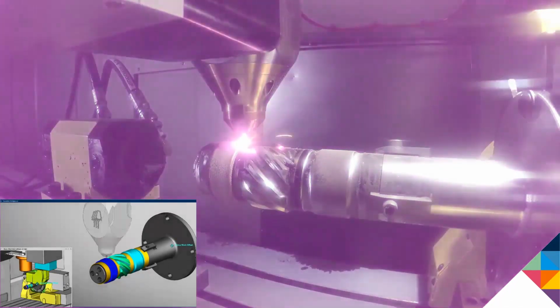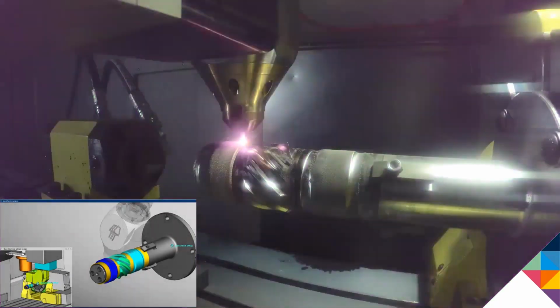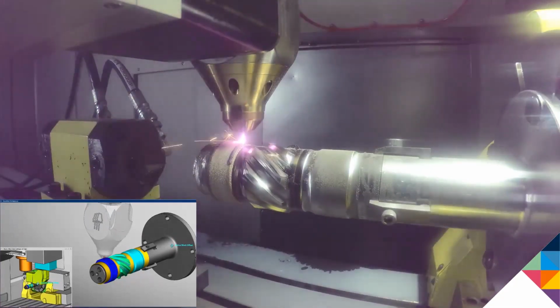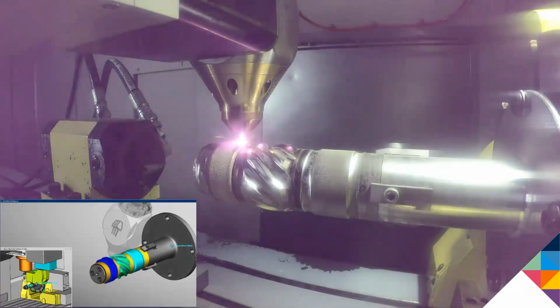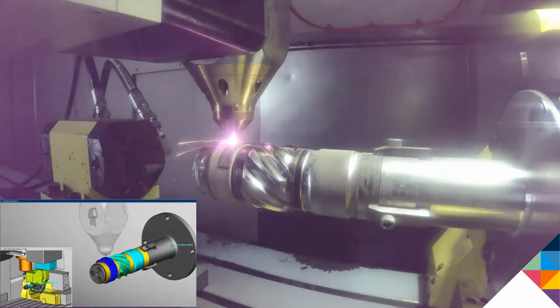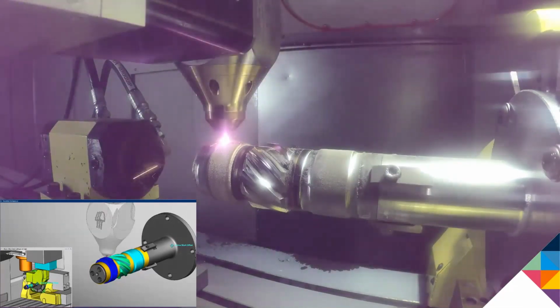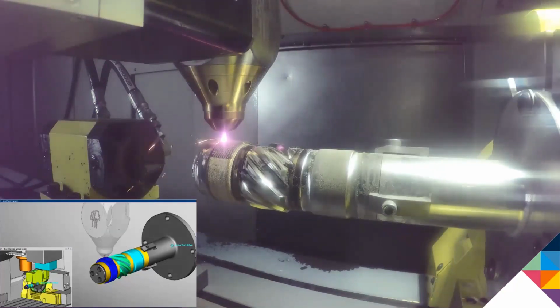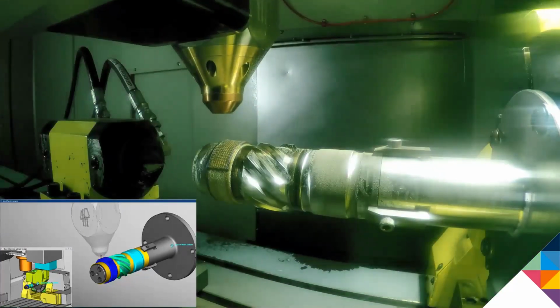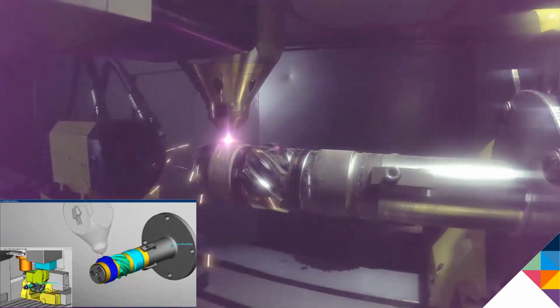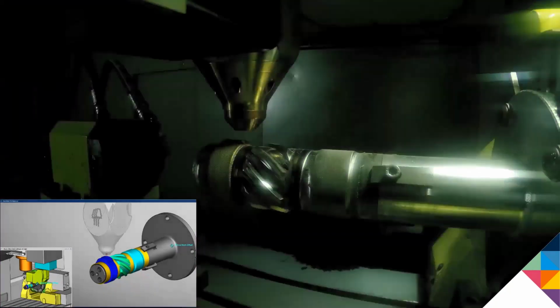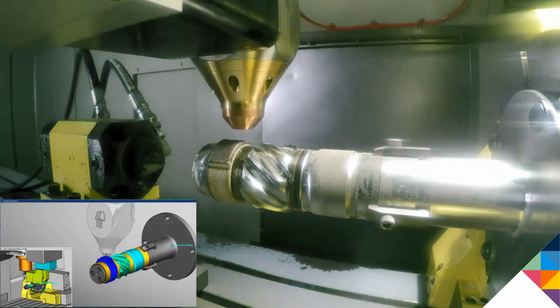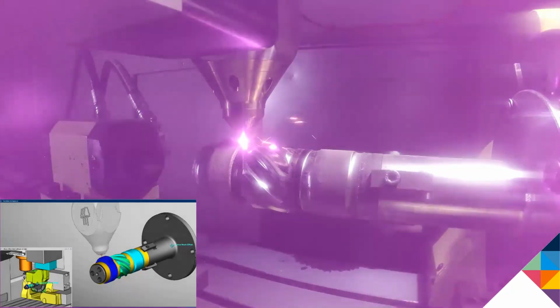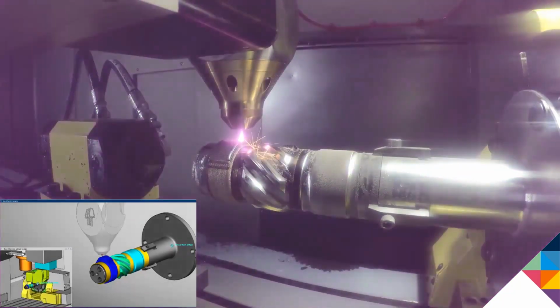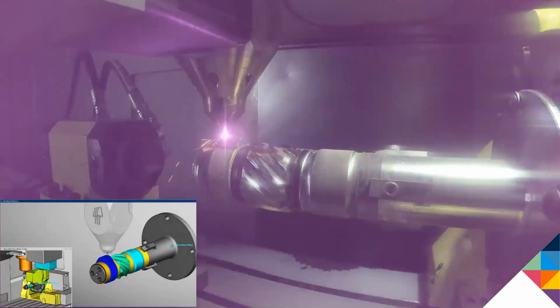So each layer on the zigzag, we switch between depositing radially around the part. That's what you can see it doing now, the radial deposition, and moving axially along the length of the part. What we found is if you stick to a single direction during your buildup, you can get a bit of a fall away at the edges. But we've also found that you get a slight lump at the start and end of some of the longer toolpaths. So by combining those with the axial and radial alternation, you end up getting quite a clean vertical wall. You can see that pattern as it builds up on the video.